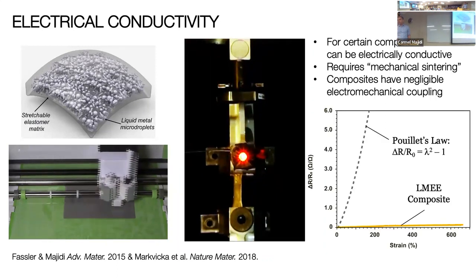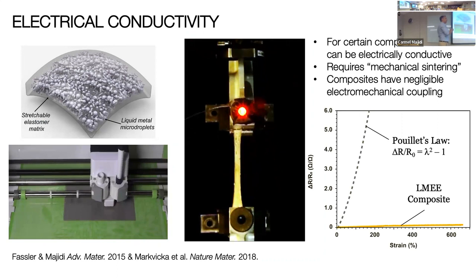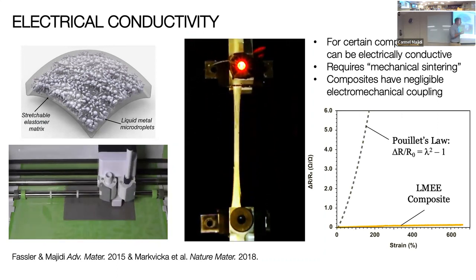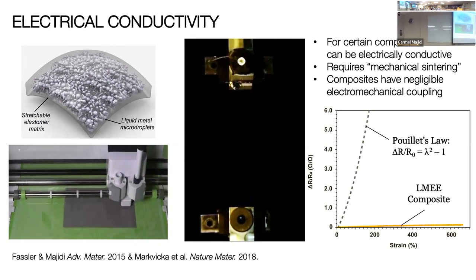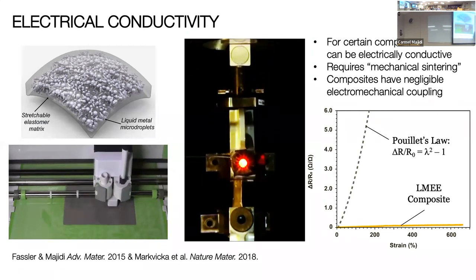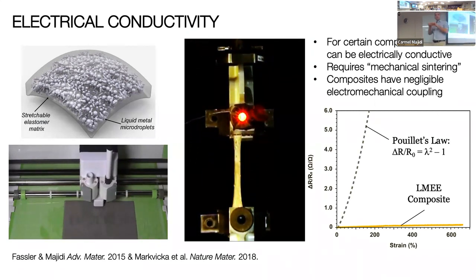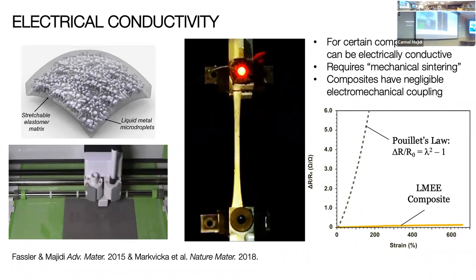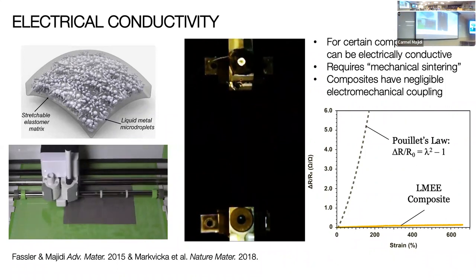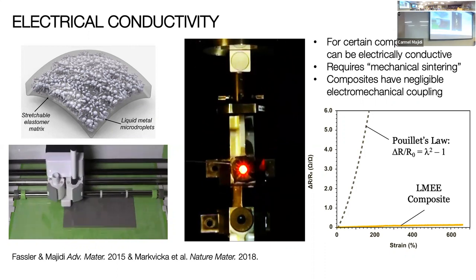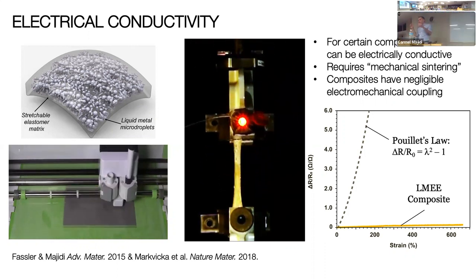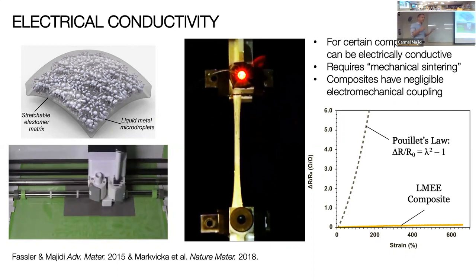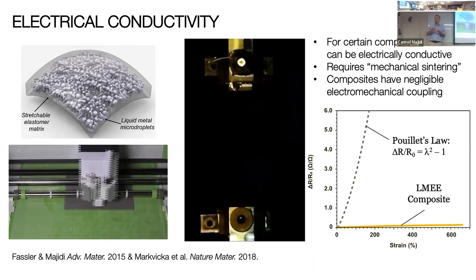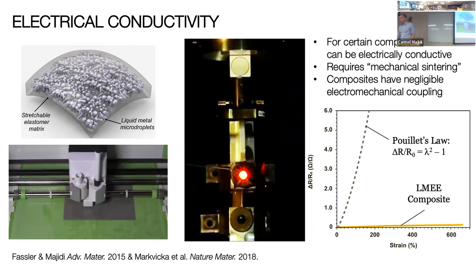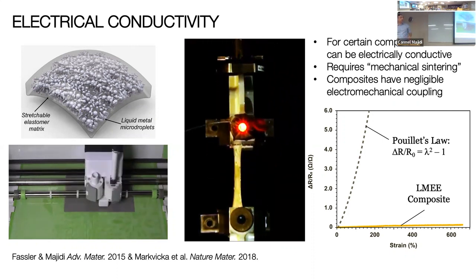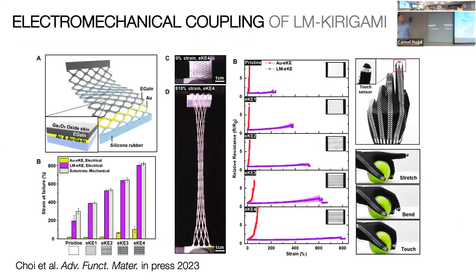We can also make versions of these composites that have very high electrical conductivity and, combined with that, very low electromechanical coupling. You can see here that as we stretch these materials, the resistance actually remains quite stable. It doesn't spike up the way you would expect for conductive materials, as they elongate and cross-sectional area decreases. We don't see that with these composites. We've done quite a bit of modeling to validate what we're seeing experimentally there. I won't get into it.